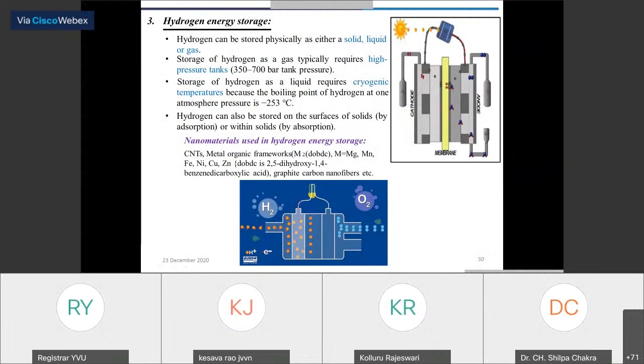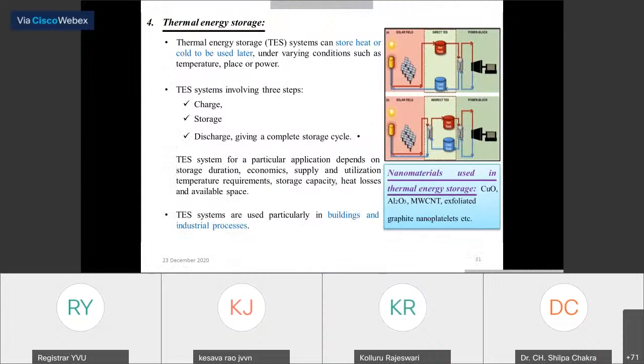And this is the third category, hydrogen energy storage. Generally, hydrogen can be stored in three forms: solid, liquid, and gas. But in this, we use nanomaterials like CNTs, metal organic frameworks, or graphite carbon nanofibers for the hydrogen storage purpose. And this is the fourth category, which is thermal energy storage. In this thermal energy storage, there are three steps. It can charge, store, and discharge with a three-step storage cycle process. And for the materials here also, you can use copper oxide, aluminum oxide, multi-wall CNTs, and graphite nanoplatelets.